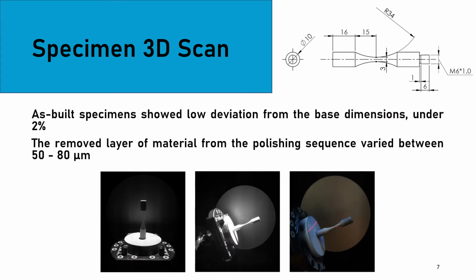All ultrasonic fatigue test specimens were analyzed in an optical 3D scanner, as we can see in the pictures on the bottom of the slide. From those scans, we took the low deviation that selective laser melting can obtain, which was under 2% from the base dimensions. Because the specimens were analyzed before and after polishing, we quantified the removed layer of the material until a mirror-like surface without any defects, which resulted in between 50 to 80 micrometers in all polished specimens.